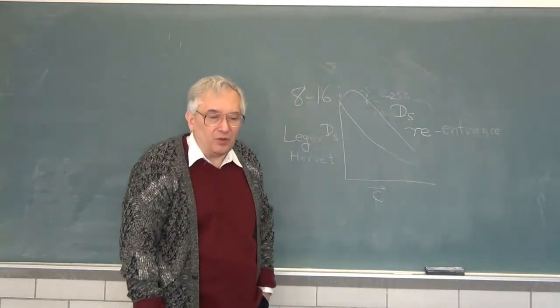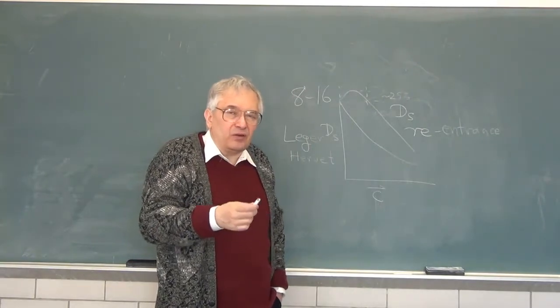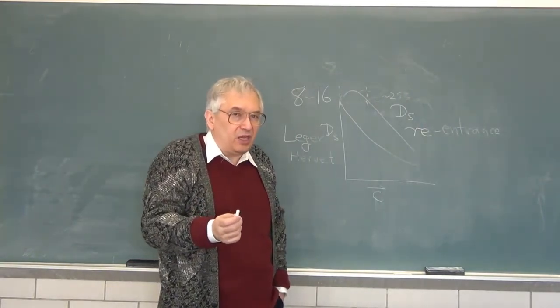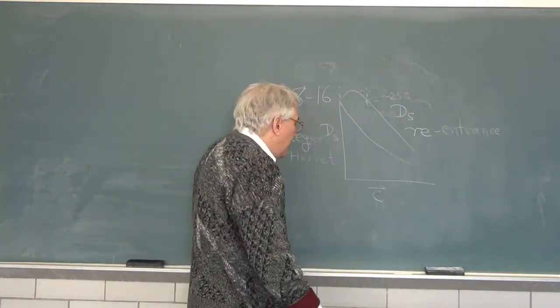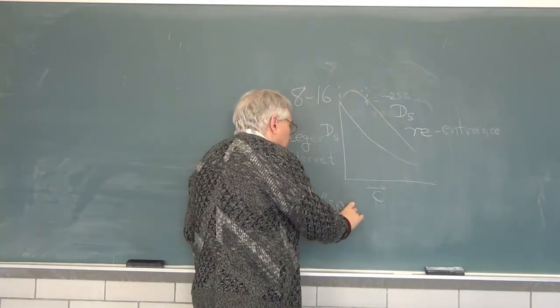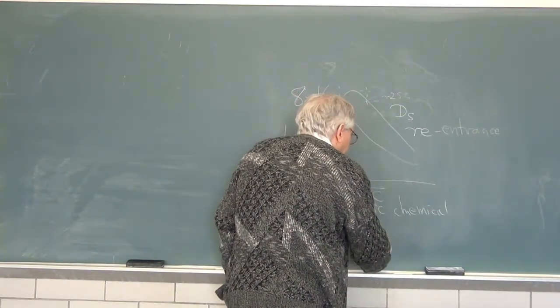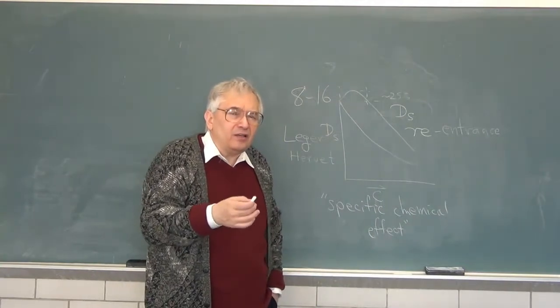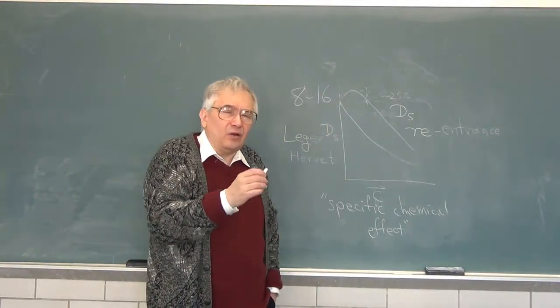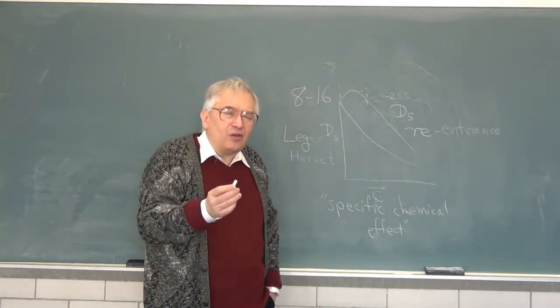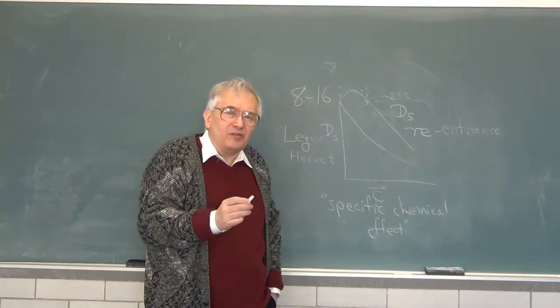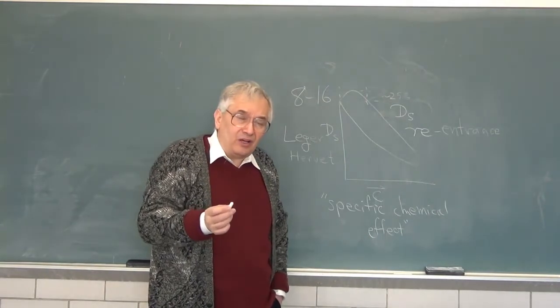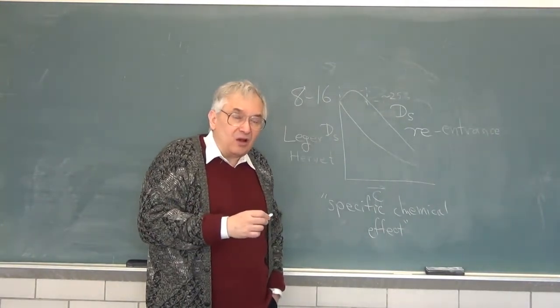In this case, what you're saying is that something odd happens at low concentrations of polymer. However, it could also be noted that there are a whole series of people who studied more or less the same chemical system, and no one else sees this effect. The magic phrase we use is specific chemical effect. The point of specific chemical effect is that you're actually dealing with the product of a complicated synthetic process, and even though you've been very careful and you've done all sorts of good things, every so often something odd happens with a particular sample of material, and you may not even realize it's happening, and it may not be worth chasing down exactly what happened.